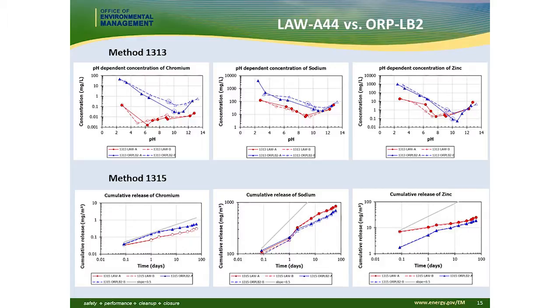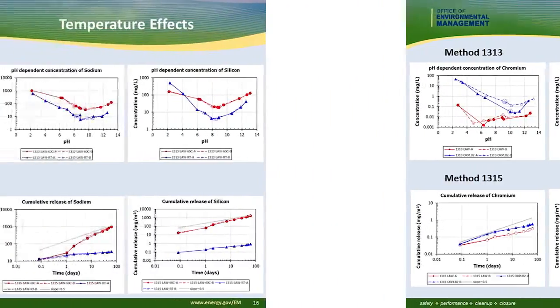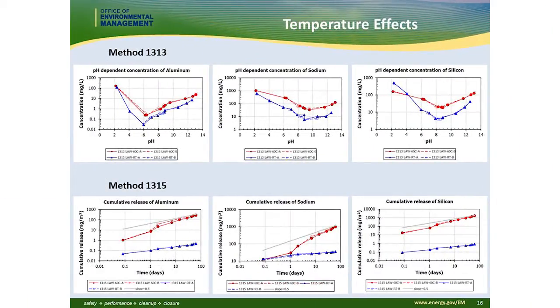So we felt pretty good about the sensitivity, and then we looked at temperature effects, and we took some bounding conditions. We just said, okay, this is at room temperature, not well controlled, as opposed to being better controlled in a constant temperature room at 22, and at 60 degrees. So we are seeing significant distinction at the different temperatures as well, which also leads us to believe that we should be able to isolate the kinetics and the thermodynamics from it.